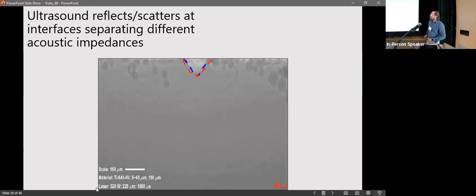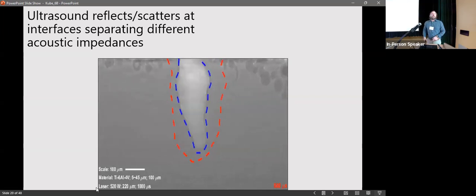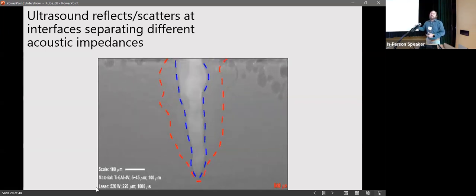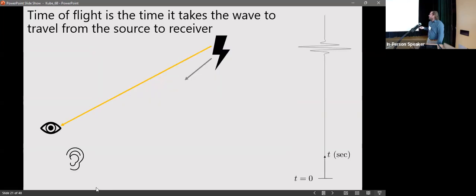For the melt pool case, we're also thinking about impedance differences. When you're melting, you're creating a liquid region. This red curve represents the liquid-solid boundary. We get scattering of ultrasound from that boundary, and that scattering tracks with your melt pool behavior. I'll be mainly highlighting time of flight measurements in this talk.